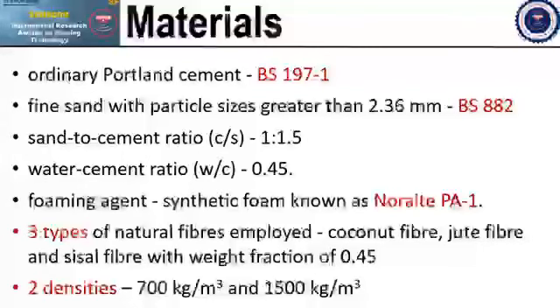Then the foaming agent used to produce the preformed foam was the commercially available synthetic foam known as Noraite PA1. The Noraite PA1 was selected as the foaming agent in this laboratory investigation due to its ability to produce a smaller bubble size, which tends to create a stronger bubble bonding structure compared to the synthetic based surfactant. The natural fibers used were, as I mentioned just now, coir fiber, jute fiber, and sisal fiber, which were freshly collected from an industrial unit after processing. As these fibers were covered by a layer of grease to prevent fungus growth and spoilage, they had to be washed thoroughly to remove the grease completely.